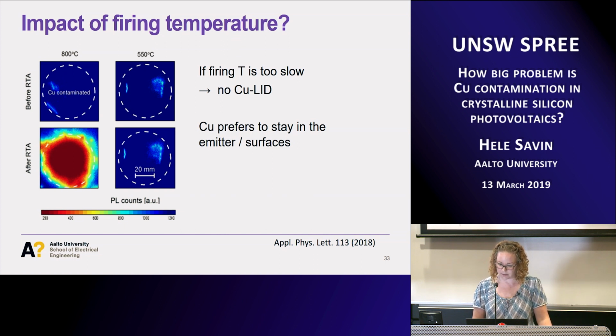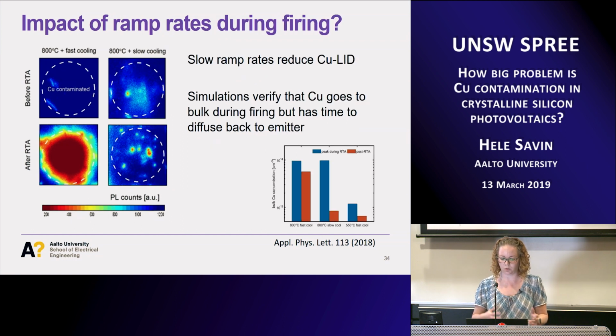And then maybe a third parameter to study in this firing is the ramp rate. There are also studies showing that when you do slow cooling after your firing, you would actually see less LeTID. And that seems to happen also for the copper LID. So if we still do this high temperature RTP above 800, yes, we are pushing the copper from our emitter to the bulk.